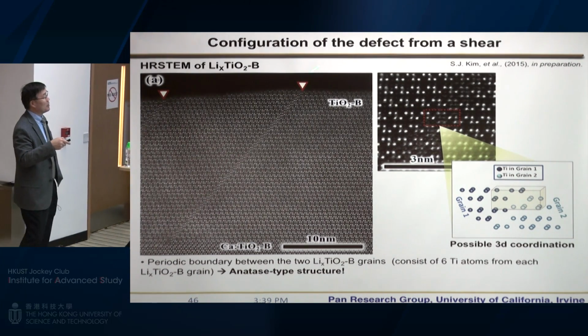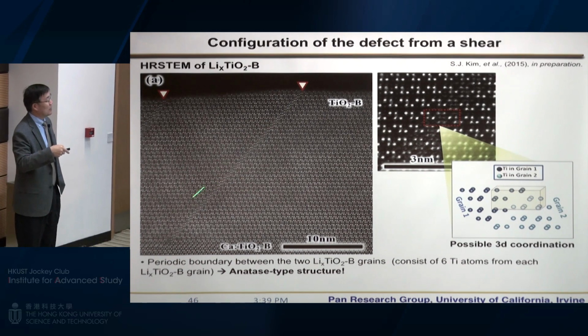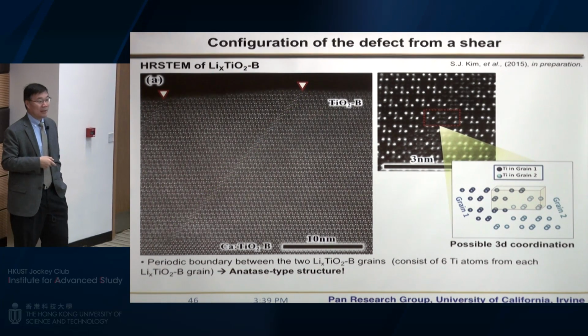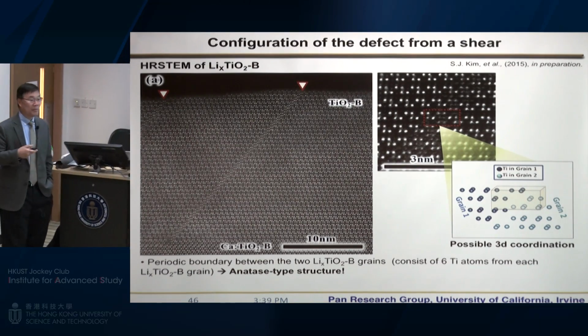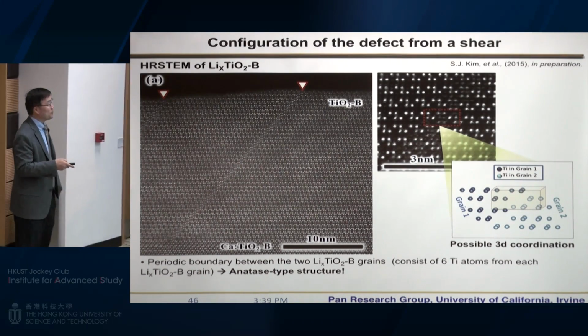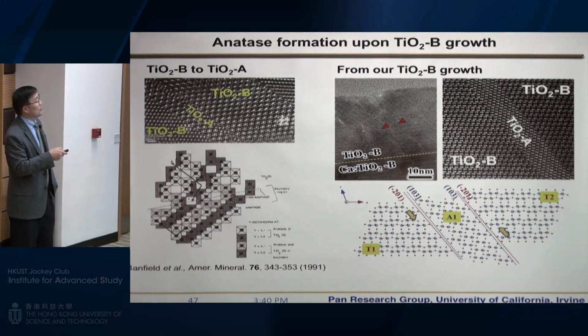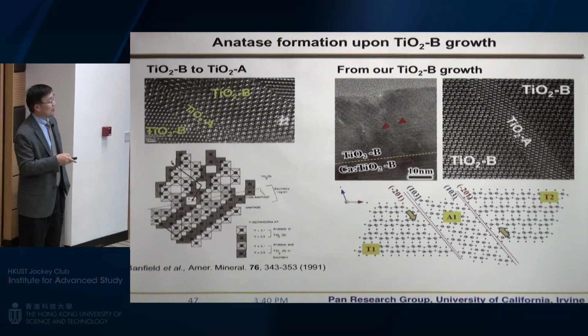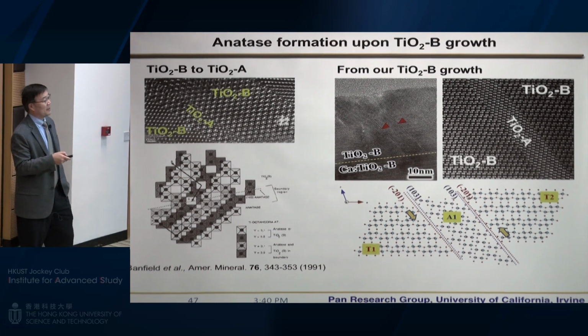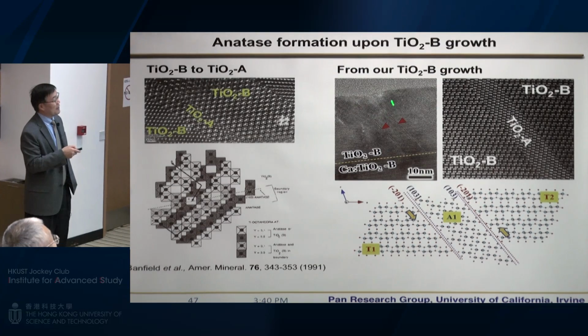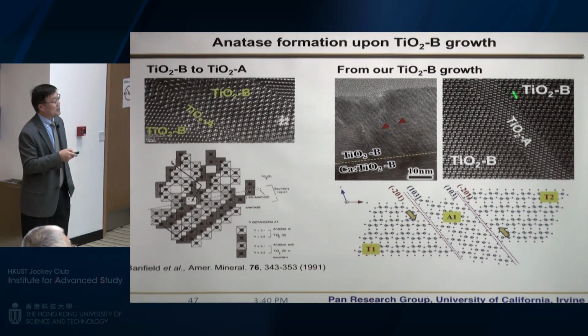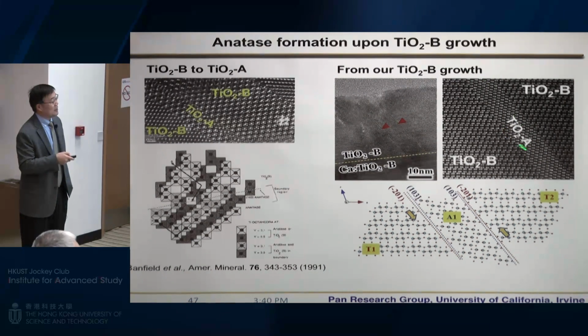As more and more lithium diffuses into this structure, you see more and more defects. It looks like the anatase phase becomes more stable during this transition. So these are all the details that Sangju studied, and they can see more, and also the anatase gets thicker, but not very thick. I hoped, when I saw that thin layer of anatase, to ask: if you continue to insert lithium, can you make this transition from bronze B to anatase and vice versa?